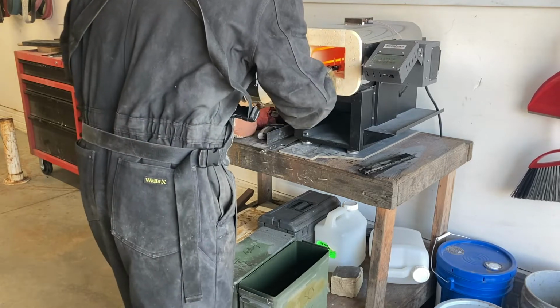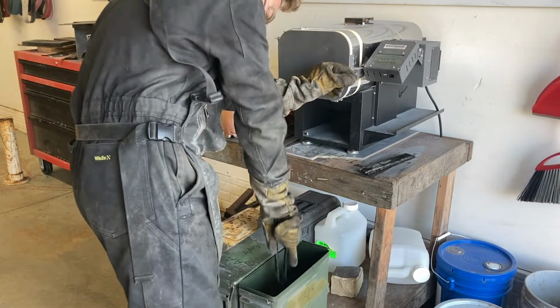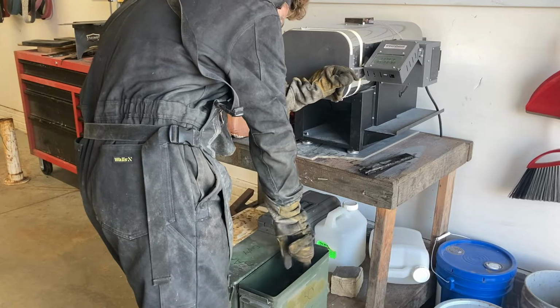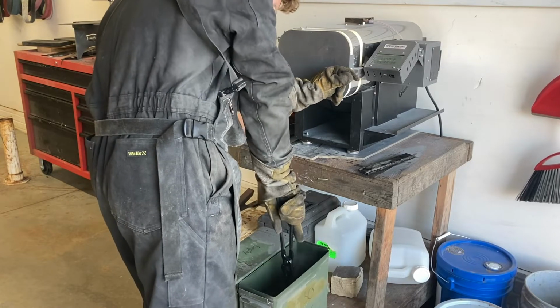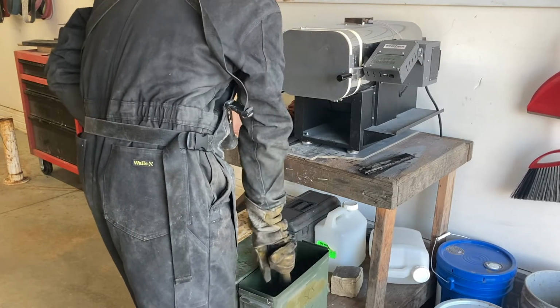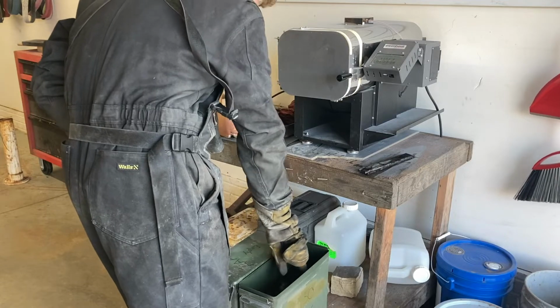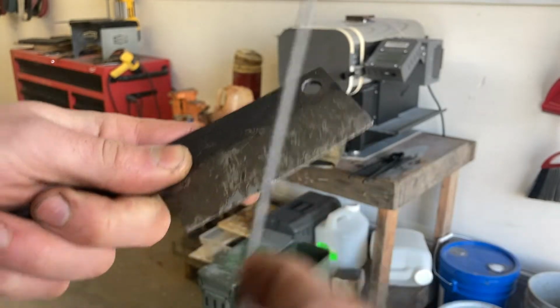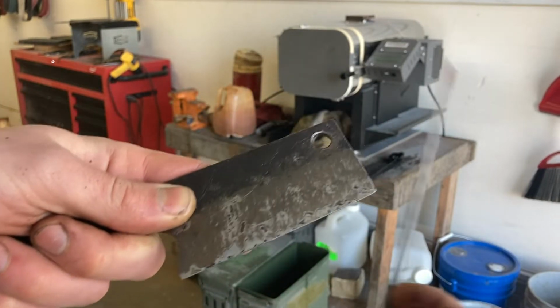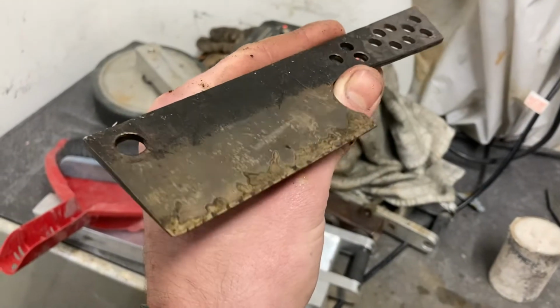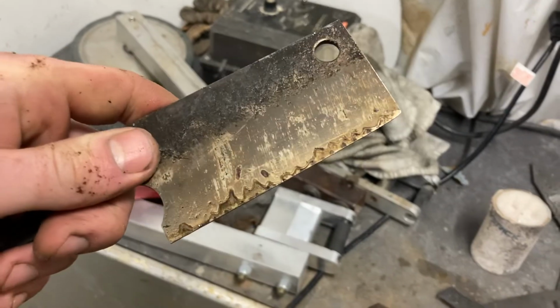The ideal temperature range for Parks 50 is around 70 to 80 degrees, so I always make sure to heat up my oil when it's really cold outside, just so that it stays in that range. Here I'm just doing a quick file test to make sure that the edge got hardened, and it skates across, so it looks like it's nice and hard. And here's the knife after tempering twice for 2 hours at 400 degrees.